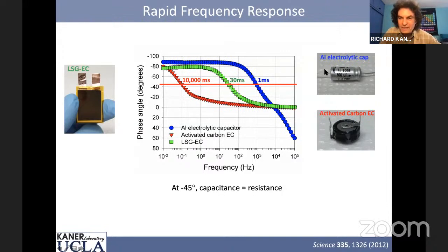It's not quite as fast as an aluminum electrolytic capacitor, which is on the order of 1 millisecond. However, this stores very little charge. It's interesting that if we could speed up this number and get down to the level of an aluminum electrolytic capacitor, you could think about using this for things like line filtering. I'll show you that this is becoming a possibility.